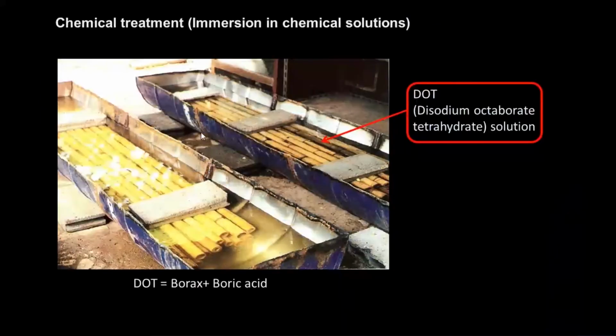And another way is chemical treatment, using immersion in chemical solutions like DOT, or disodium octaborate tetrahydrate solution, which is a mixture of borax and boric acid in special proportions. You can immerse for 1 week, and after drying, you can use it easily without any problem of insects or other attacks.